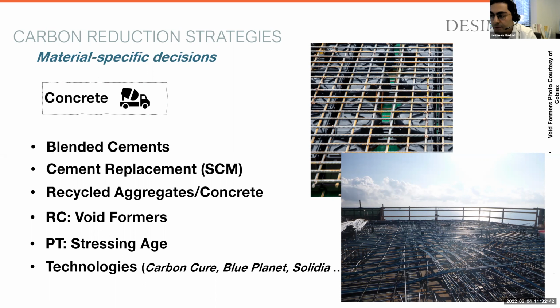Then you have cement replacement options, and now we are talking about fly ash and slag and ground glass and other supplementary cementitious materials, as they call them. It's a great option, but it has some complications when it comes to real design of a project. Great in the sense that if you assume that fly ash and slag are almost zero carbon intensive compared to cement, if you're replacing 50% of your cement with fly ash, you're reducing 50% of the embodied carbon of concrete. That is fantastic, and I think it can be used in many elements in a structure, including a foundation.